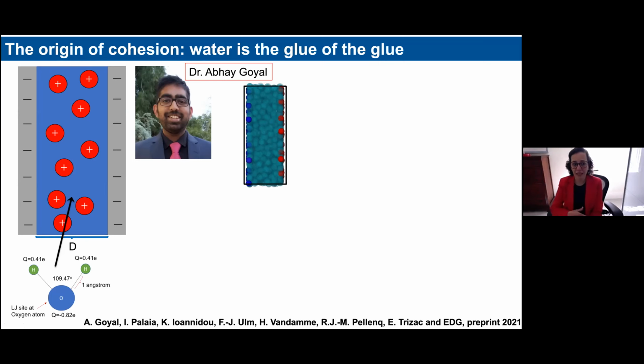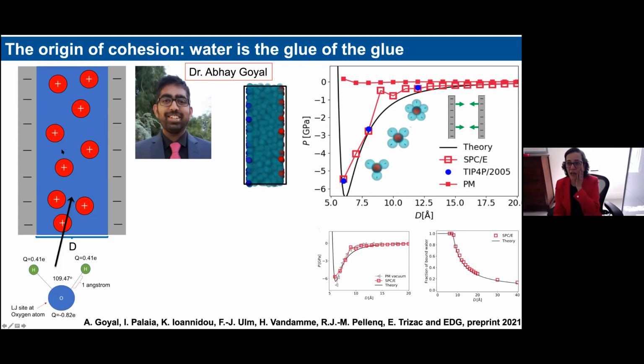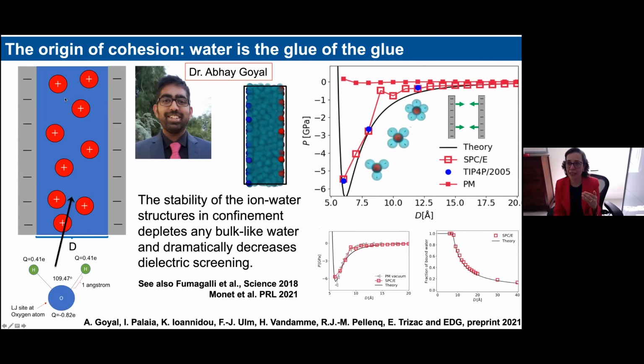During his thesis, he devised this model in which we consider explicit water. We used SPC/E water, and we did some tests also with TIP4P water to make sure that our results were not really affected by the choice of the model. When you do three-dimensional simulations of these charged surfaces with the ions in between and explicit water, you realize that the situation is quite different, because the ion and water structuring in confinement changes completely the net forces between the two surfaces.